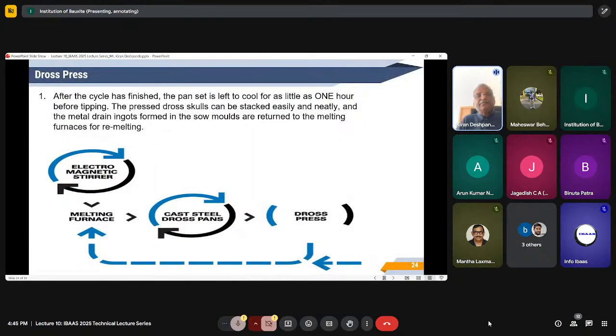After the cycle has finished, the pan is left to cool. So you take the pan out, keep it for cooling for 1 hour, and then you just tilt the pan with the forklift. The shape of the pan is such that the entire skull comes out as one piece, rather than disintegrated powders or something like that.